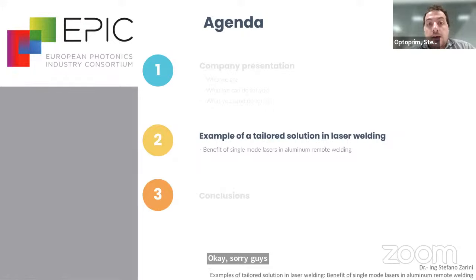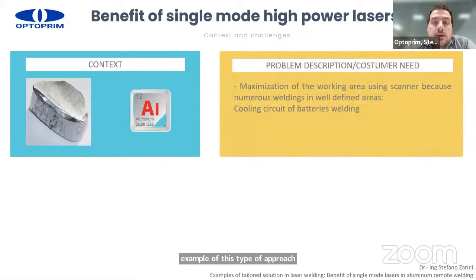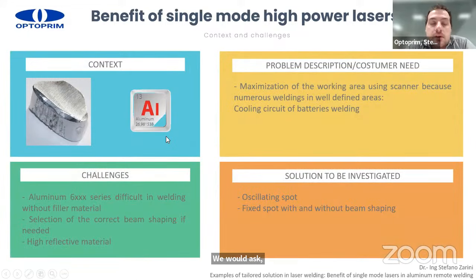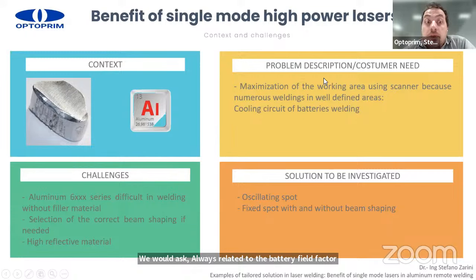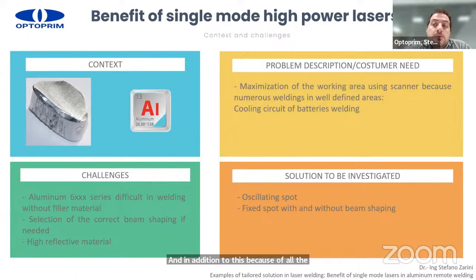So let's go to an example of this type of approach. We were asked, again in the battery sector, to maximize the working area of aluminum welding plates. The plates were made of 6000 series aluminum, which is difficult to weld. Because of all the possible solutions mentioned before, such as wobbling and beam shaping, we were also asked to identify which is better for this type of application. So we made a comparison between a wobbling solution and a fixed spot with and without beam shaping.